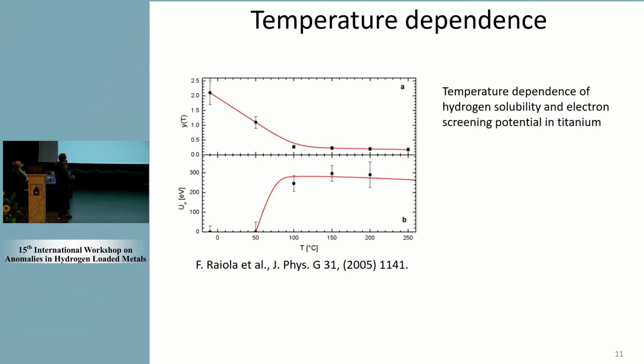This is for titanium, which at room temperature had very low electron screening, but then when they increase the temperature, the solubility changes, and they got a high electron screening potential of about 300 electron volts. But this is not directly related to temperature, but to changes in the structure of titanium and hydrogen in titanium when you increase the temperature. So this is just somehow coincidence with temperature. So it's not directly temperature related. But okay, you can see that already here. There are differences in the same target depending what you do with it.